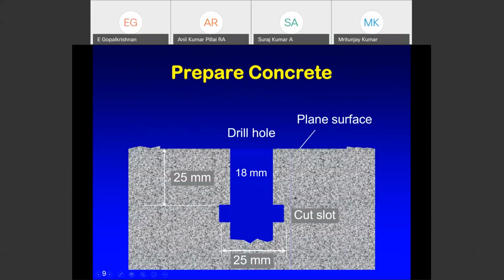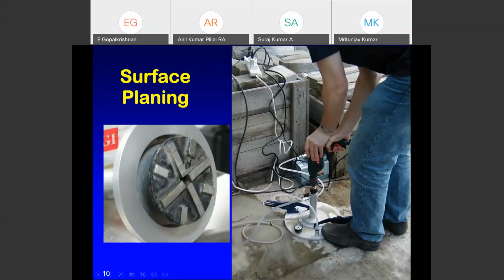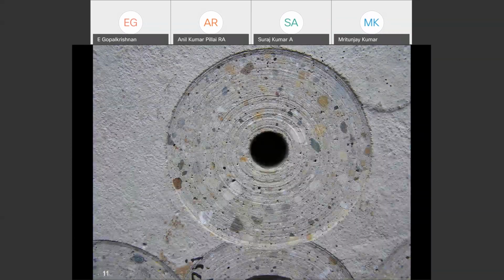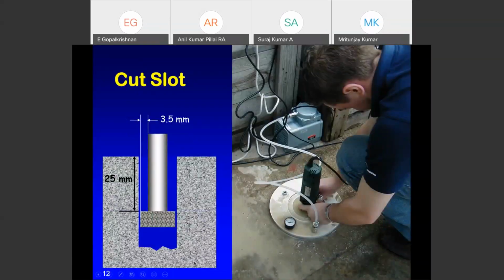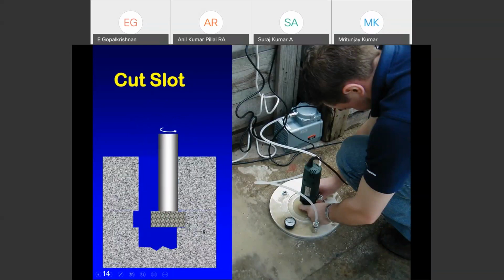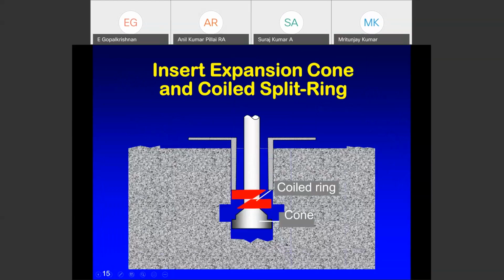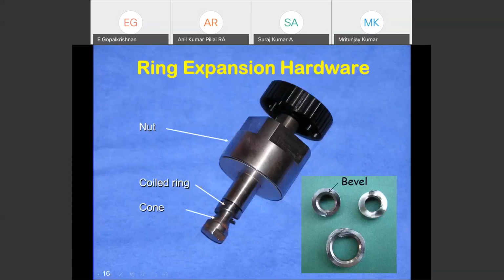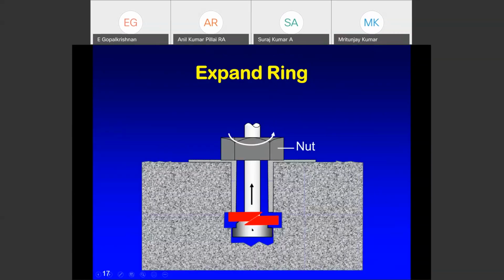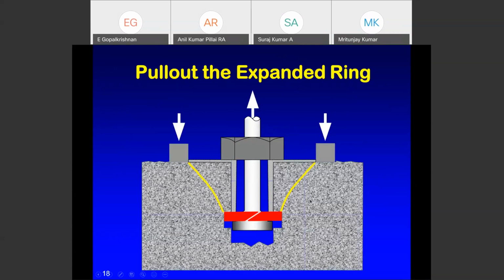I can show you the preparation of the concrete: drilling an 18 mm diameter hole, almost 65 to 70 mm deep. We can insert the ring in the special slot. Surface preparation is done with a diamond edge drilling machine. We need to achieve a smooth surface. Then we need to prepare the special slot; a special drill is given to do that, where we are going to fix the coiled ring, which is going to expand. This coiled ring looks like that. We are able to pull it out. When you are pulling out, we will get the break in a V cone shape.